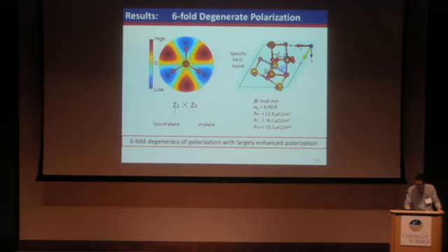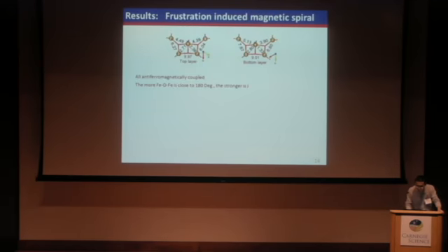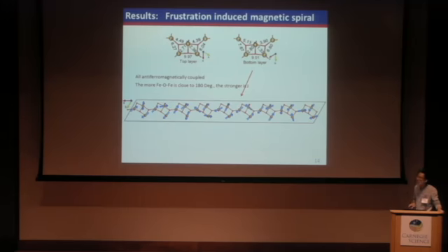in the hexagonal phase. For the magnetism, we calculated the iron-iron exchange coupling, which is all iron-oxygen-iron coupling. It is found that they are all antiferromagnetically coupled. And the closer this angle is to 180 degrees, the stronger the coupling J is. The most interesting thing is that the specific structure and the antiferromagnetic coupling result in a spiral magnetic ground state.